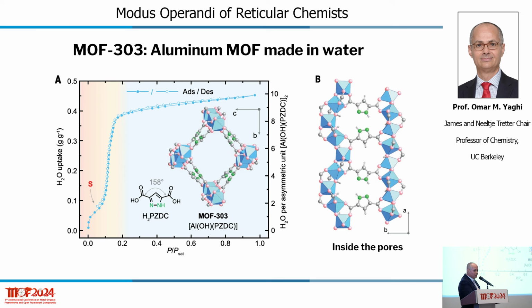And this is something that we couldn't design yet, okay? And that is that the material, when you look at the interior of the material, you have hydrophilic sites and hydrophobic sites, hydrophilic and hydrophobic pockets into which water goes. Water goes directly to the hydrophilic sites and bridges over the hydrophobic sites to make a material that has what I call a push-pull interaction with water.